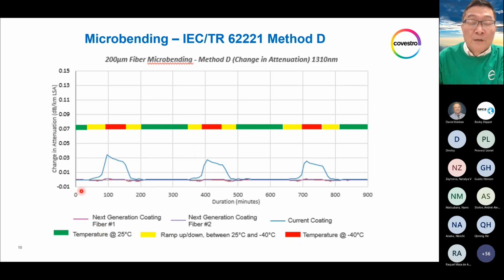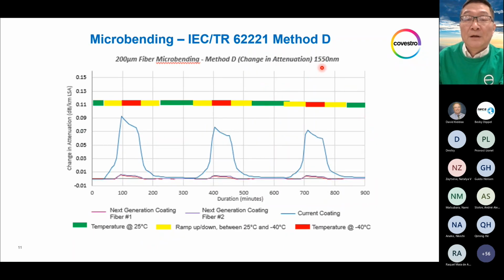There are two fiber samples. They're more or less the same, right? Over the 3 cycles, the maximum change in the current coating also reduced because of relaxation. But it gives you an idea of a much reduced microbending in the next generation coating system because of the reduced mechanical properties in terms of the modulus. To give you an idea of the benefits, the same microbending was also tested at 2 more different wavelengths, 1550. You see the same trend. The next generation coating system has much more reduced change in attenuation at 1550 than the current coating.